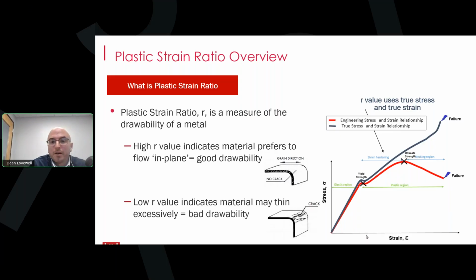This distinction matters because while engineering strain is based on the specimen's original dimensions, true strain accounts for the continuous reduction in area that occurs as the material deforms. Similarly, true stress uses the instantaneous cross-sectional area, giving a more accurate representation of the actual load-carrying state of the material. Now, the reason R value must be determined from true strain is that it specifically represents a ratio of instantaneous plastic strains in different directions, which evolve continuously during deformation.